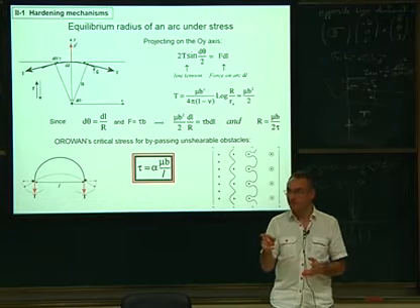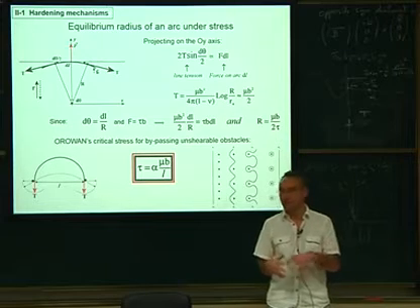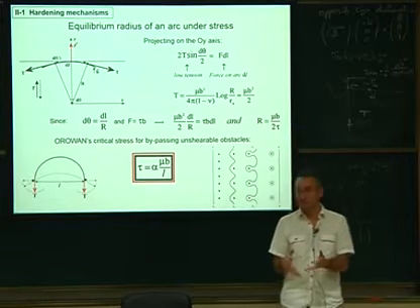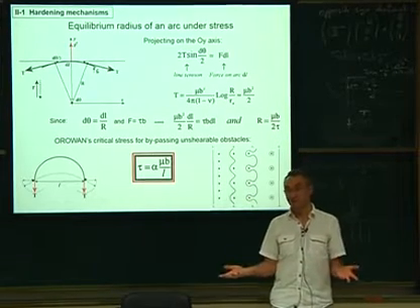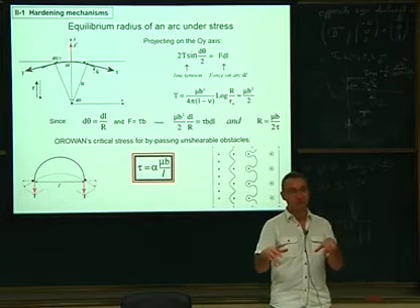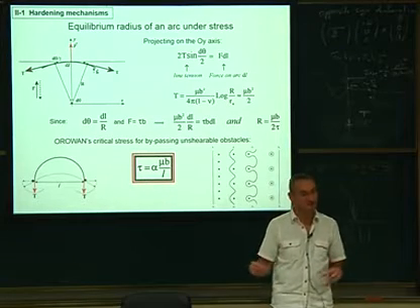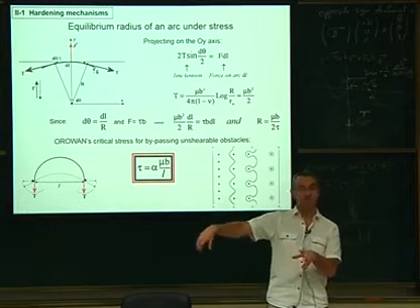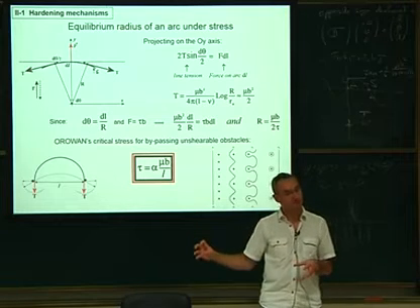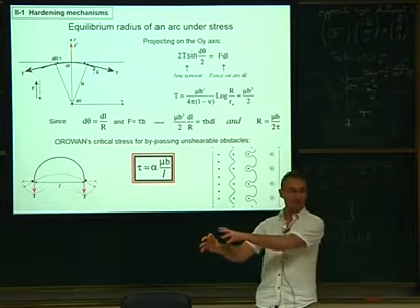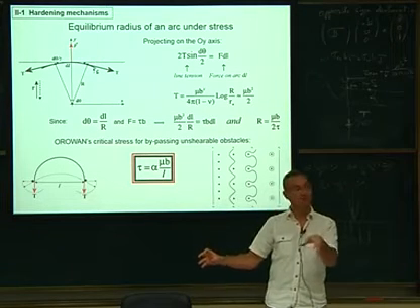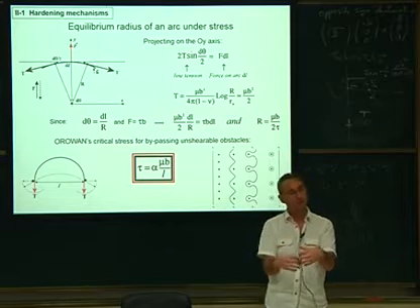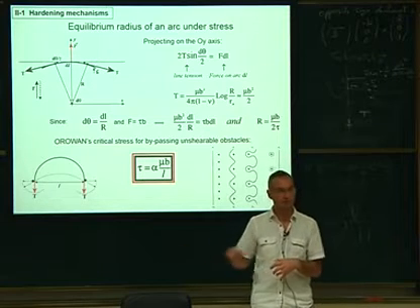Temperature could be, yes. Dilatation, temperature, that's a good point. But more easily than that, the other dislocations. We saw this morning that when you have two dislocations together, they interact. So just imagine that there is a wall of dislocations, a pile-up, or maybe a dipole, like we saw this morning, at a given place. This dipole generates a stress somewhere. At that place, you have a stress. So if there's a dislocation here, it will be a little bit bent because of this stress locally.